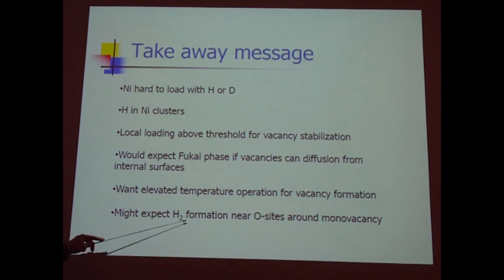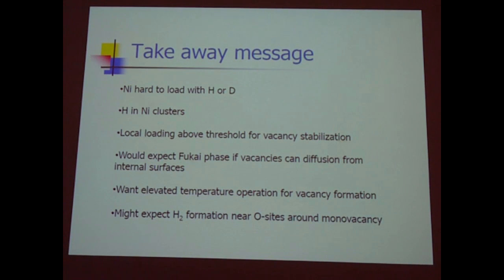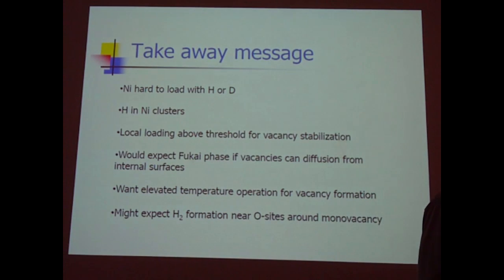And if excess heat in palladium is due to D2 formation near a vacancy, density functional calculations have been done for a similar vacancy system in nickel. It's basically the same, the local environment. The arguments are almost identical.